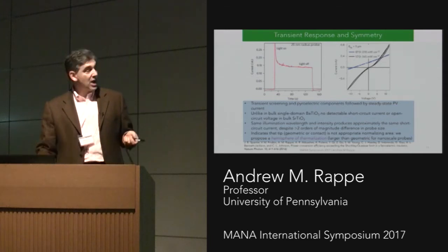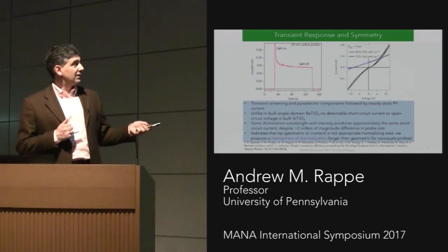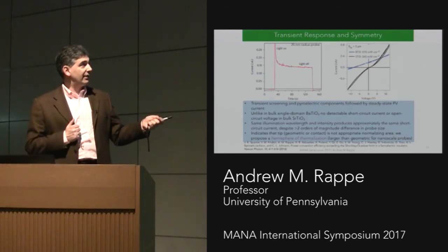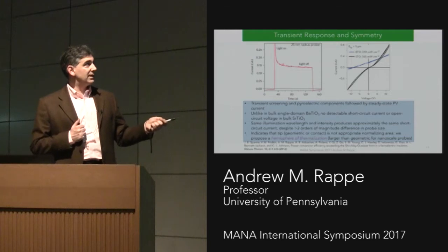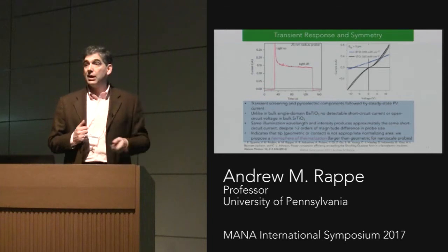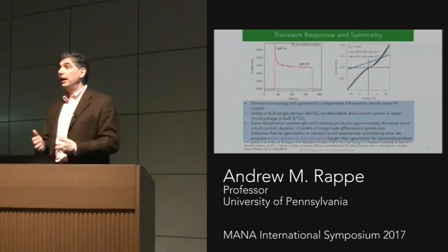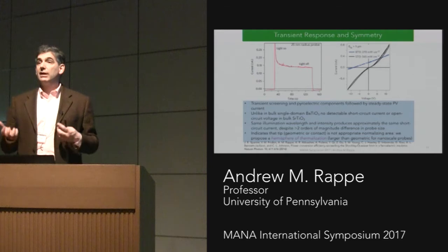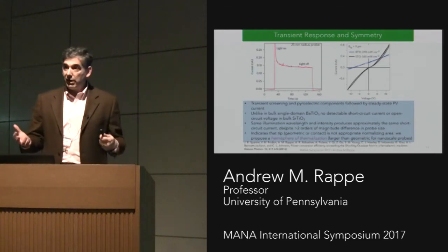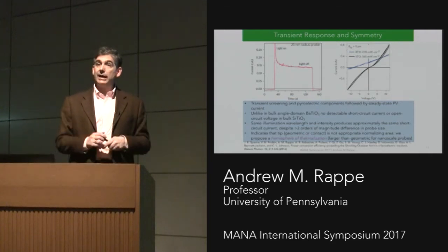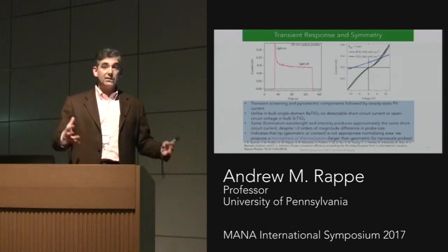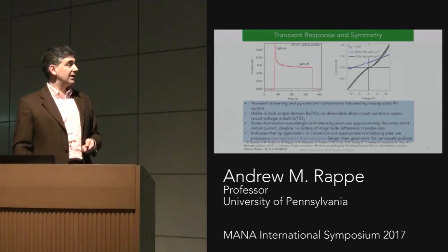Okay. So the experimentalists ran this experiment with the sharp tip with a 25 nanometer radius, but also with a much more blunt tip with a 5 micron radius, and the photocurrent is just about the same. So this shows you that the tip radius is not the relevant collection radius that sets where the current is coming from. And so again, we are saying that it is really a quantum hot carrier effect, and the thermalization radius for these hot carriers sets the region over which the experiment is collecting current.